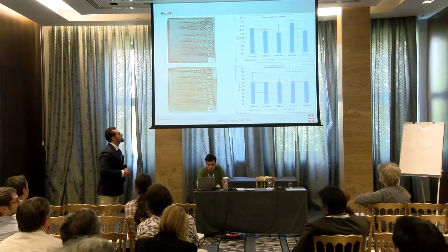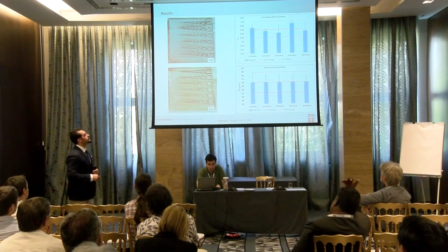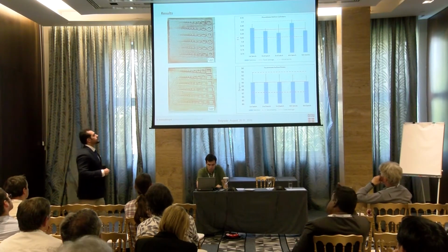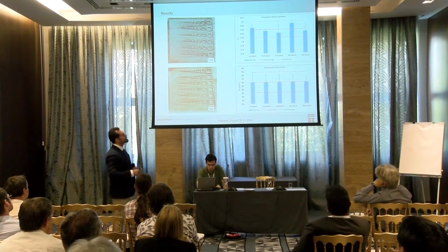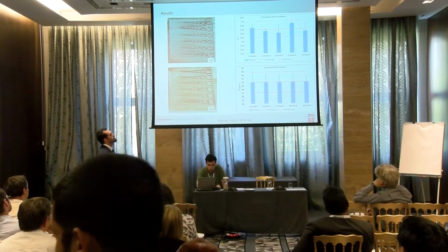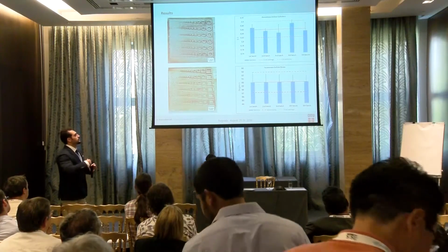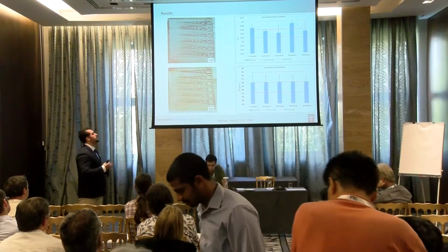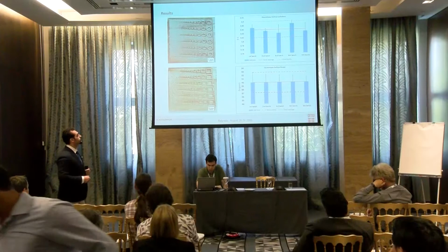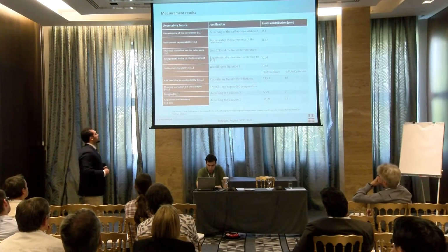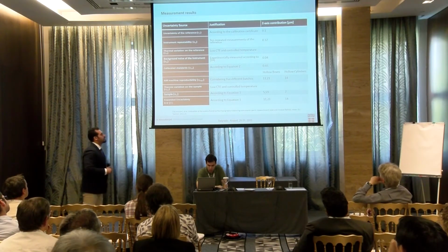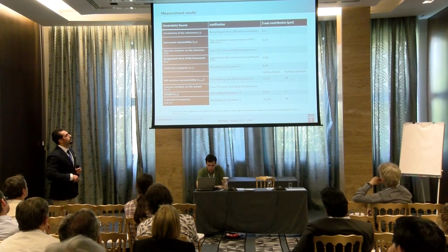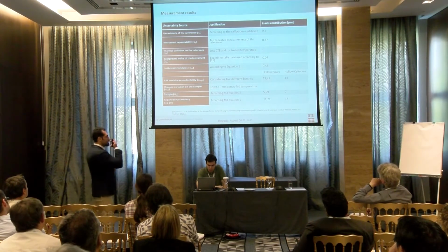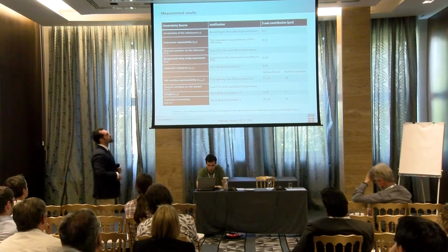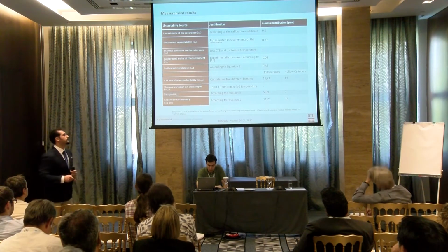And this is the result of the roundness and the squareness. We had a more uniform result in different batches for the squareness than for the roundness. In roundness, we have a bit of variation in each batch of print. Then finally, in terms of the uncertainty, it was 11.25 micron in the z-axis contribution, mainly for the hollow box, and 14 micron for the cylinder.